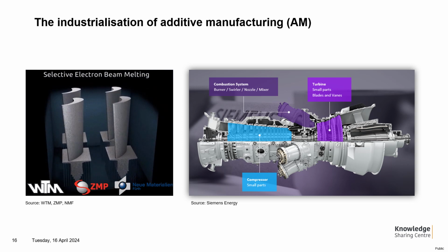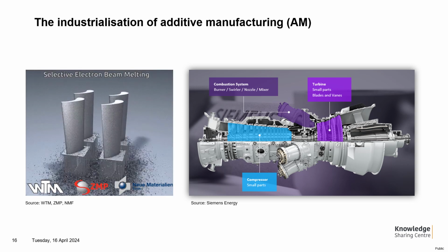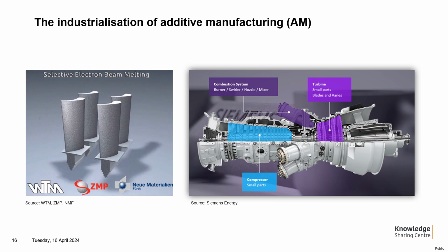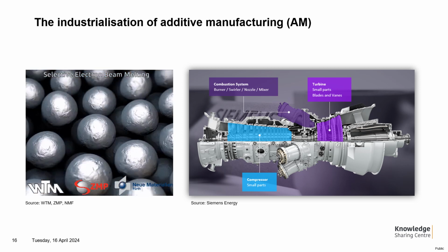Because normally nickel-based turbine blades are classified as non-weldable, but nowadays with preheating strategies they can also be manufactured via additive manufacturing. But there is still a big hurdle to take for AM, because a ready-to-use part directly after printing does not exist.